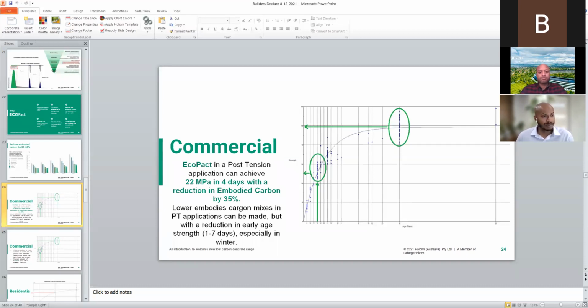I'm pleased to announce that with EcoPact, Shashank and I have, more so Shashank, he's done a lot of work behind this, and he's very confident that we can actually achieve 22 MPa in 4 days while also reducing our embodied carbon by 35%. Now, we can reduce that embodied carbon further, but if we did, the consequence is that the 4-day strength of 22 MPa would creep up to 5 days. And if you reduce that even further, it would creep up to 6 days and so forth. But on average, this industry typically calls out for 22 MPa at 4 days. And I'm very pleased to announce that we can offer you an EcoPact version of a PT application.